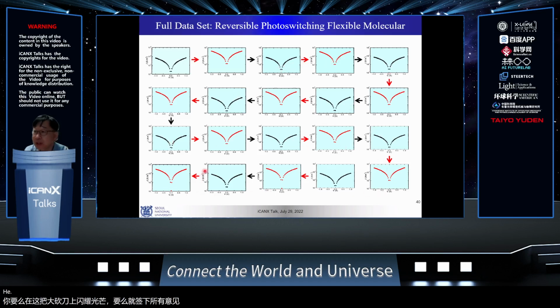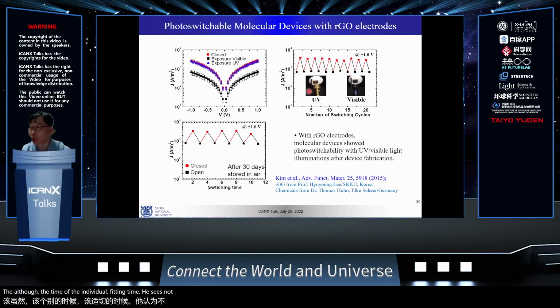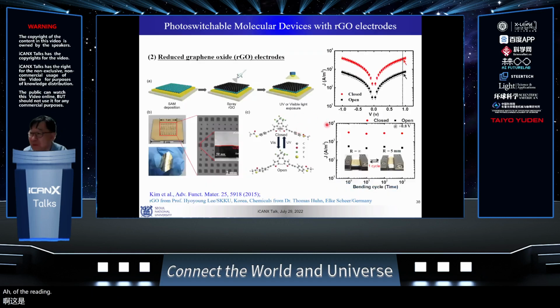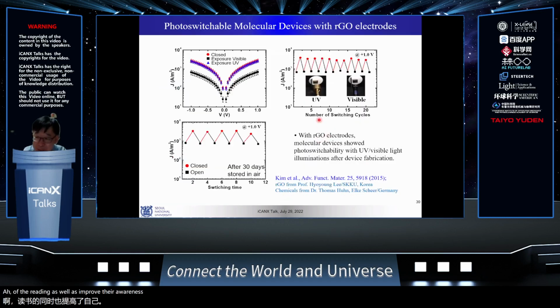Okay, although the individual switching time is not short. If I remember, it is more than like 20 minutes. It's not like 1 minute or 1 second. It's like tens of minutes, which is still really slow. There's room for improvement, but at least we have a possibility of a single molecule junction with a high yield as some kind of function.